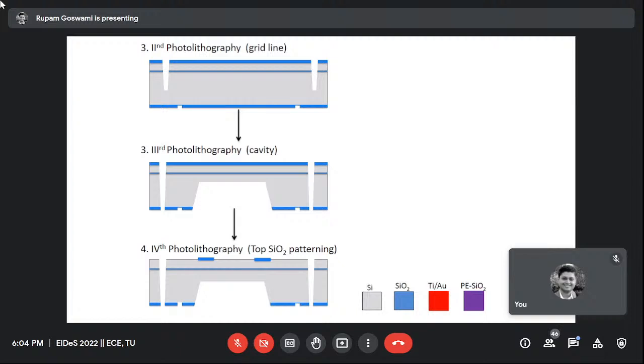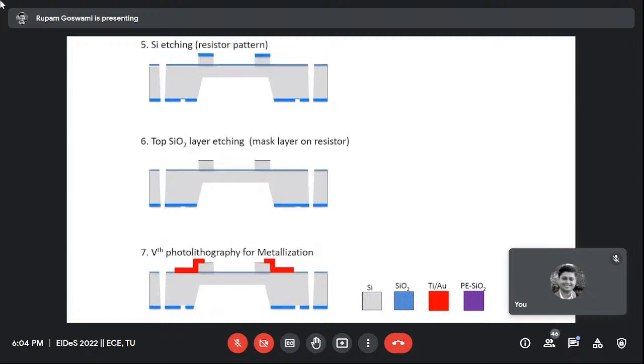And then, next slide please, the patterning using lithography, and then the active layer has to be etched out selectively to define the resistors of that active layer which was on the top. So this process is a simple process, and if the SOI wafer is of required specifications, then only 4 or 5 processes are there, and you can make the whole thing. And this is going to be very industry compatible, and repeatability will be very high here. Next, please.